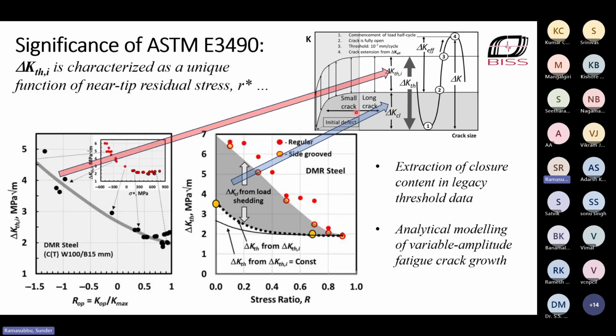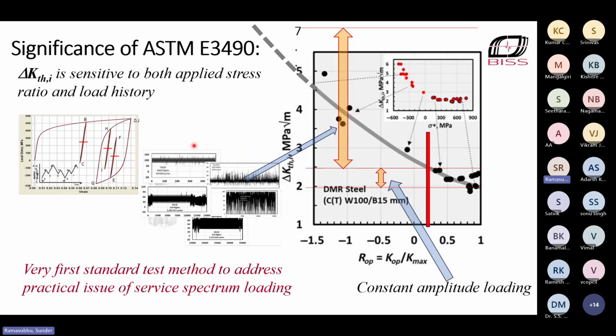This relationship becomes even more important under service loading, because when you have a load history the crack tip is going to see variations in local stress, because of stress strain hysteresis. And because of that, on a cycle by cycle basis, it's going to see a different threshold. So that is the margin of variation you can expect in intrinsic threshold if you look at real service load spectra for different structures. And I'm really happy that we finally have a test method which addresses a practical issue of service spectrum loading. So this is the first standard to determine a material property that is sensitive to load history, and it can be modeled.